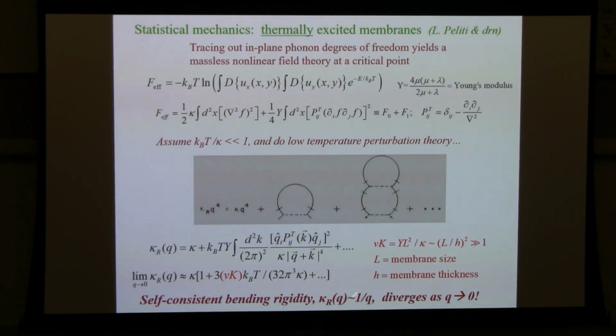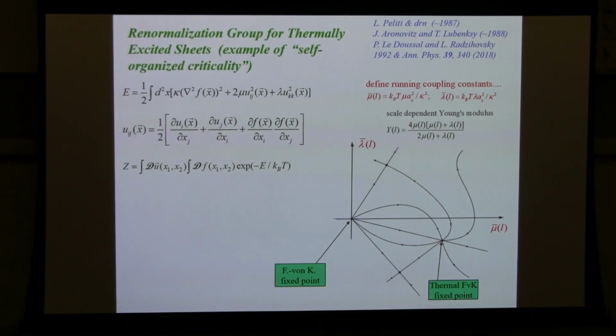And it doesn't just diverge like some logarithm. In this two-dimensional problem, it's diverging like 1 over q. So there's a very strong dependence, it turns out, on the size of the system, basically. And this is the essence of an elastic constant which is not a constant. And when you have these problems with divergences, you can do self-consistent graphical summations. But a better way to do it, typically, is to use the renormalization group.